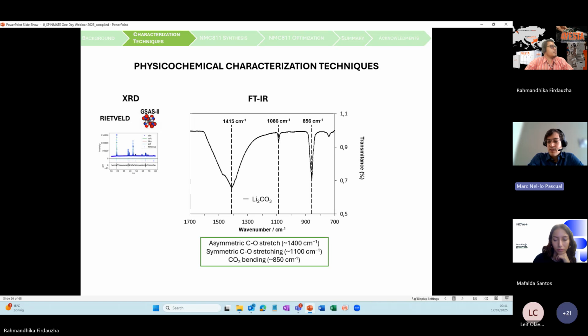The next technique that I want to mention is Fourier transform infrared spectroscopy, which is a very sensitive technique to surface impurities, in this case carbonate impurities, having these broad absorbances of the carbonate bonds in these regions of 850, 1000 and 1400 wavenumbers. So this is a powerful technique to be able to identify if there are carbonates on your sample surface.